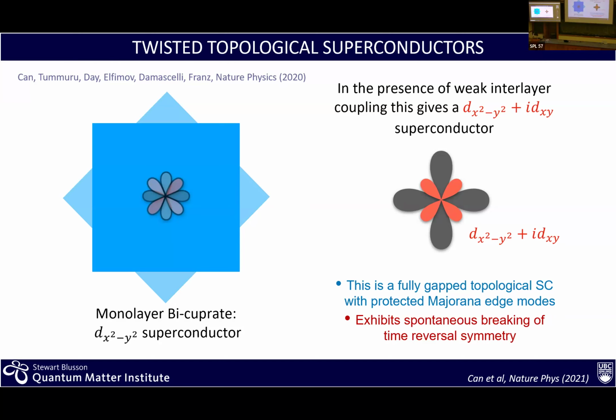Please. So if the interlayer coupling is so weak that the superconducting property remains the same in the monolayer, what would be the energy scale that, due to this interlayer coupling, induced this i term? Okay, so the question is, sorry, I should repeat the questions for the people online. So the question basically is, is the interlayer coupling strong enough to give you something like that or not? Basically, if there is no interlayer coupling, you just get two pieces of superconductor with a different orientation for a superconducting gap, and nothing happens.